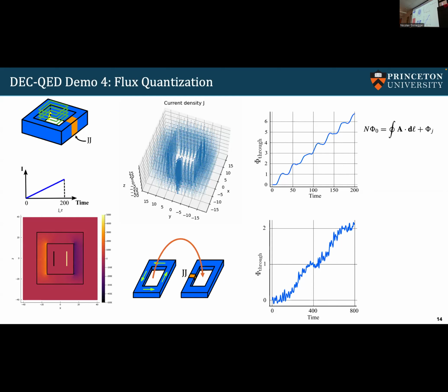This is nice, but typically when flux quantization is discussed, we often fall back to the static explanation: one would draw a line loop across the hole and argue that because the order parameter has to have unique values at every point in space, the superconducting phase around the loop has to be integer multiples of 2 pi, and hence flux is quantized. But the actual dynamical process of how that happens is usually not very clear or discussed at all.